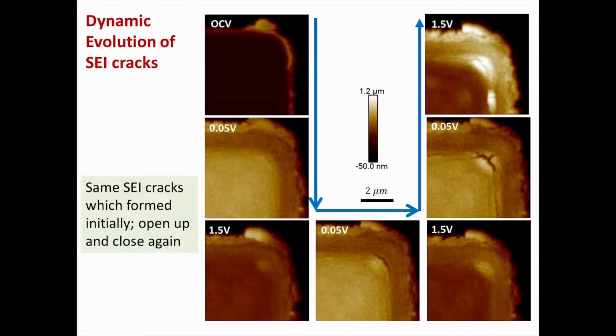Another thing that we observed is that as we start lithiating, the cracks start appearing in the edge and corner regions, and these same cracks keep evolving further.